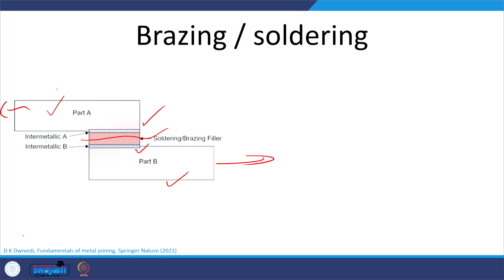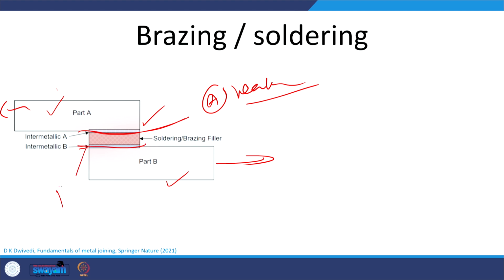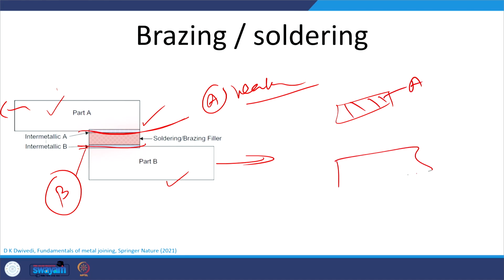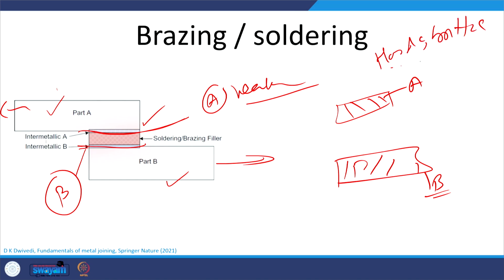Okay. And this is also possible, like if the failure occurs from the interface intermetallic A, that is the filler and the part A interface. If this is failing, means this intermetallic A is weaker. Okay, or intermetallic B is weaker if it fails from the other side. So, that makes the problem a little difficult, like it becomes the case where we have to modify the intermetallic A or intermetallic B in such a way that it has more favorable characteristics, and most of the time what we get are hard and brittle intermetallic compounds. So, if it is very hard, very brittle, then this will lower the load carrying capacity, lower the ductility, okay, of the brazed or soldered joint which is being formed.